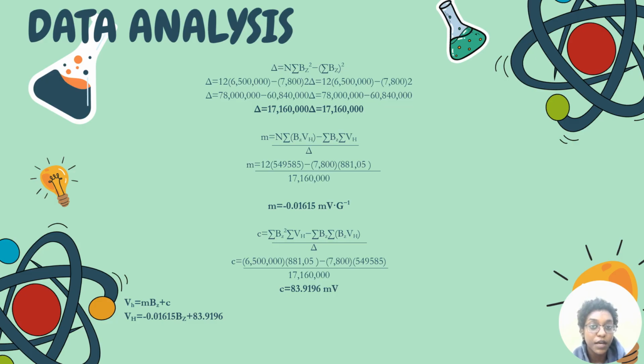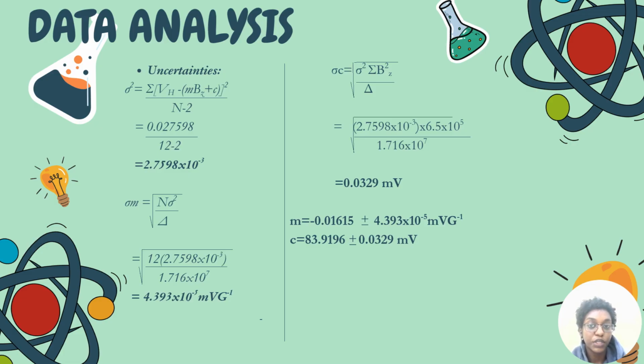Our next step is to obtain the slope and the intercept, and since we used the least square method, this is how we obtained it. We just followed the equations accordingly, and the result was VH equals minus 0.01615 multiplied by the magnetic field plus 83.9196. And then, of course, we went ahead and got the uncertainties for both the slope and the intercept. And again, just plug them in with the slope we obtained first and the intercept.